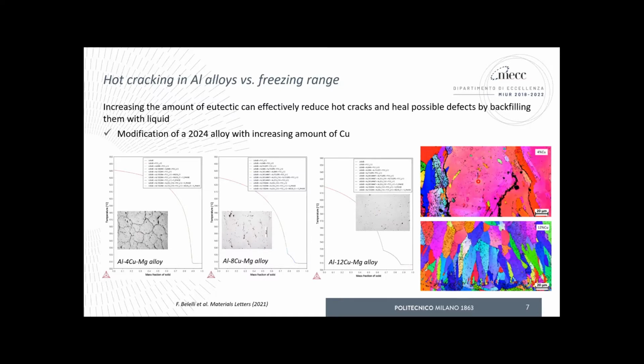Also, there is another issue that can be considered. On the right-hand side, we have the EBSD images of some grains. On the top, we have the structure corresponding to the standard alloy with cracks and coarse grains, while on the bottom, we have the 12% copper, which shows no cracks anymore, of course. But also there is a slight refining effect, which might be due to the different temperatures of solidus and liquidus especially.